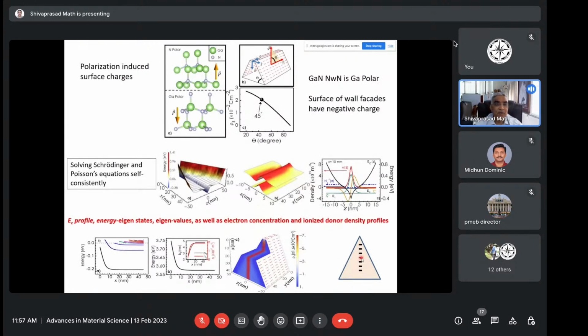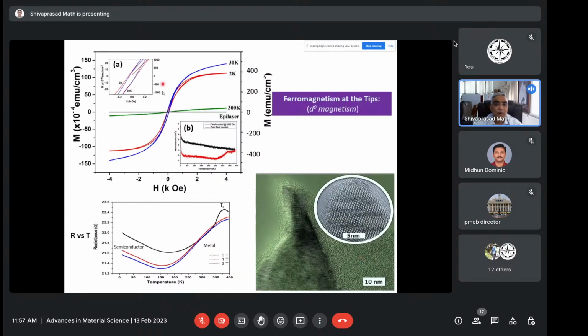Then obviously Professor Rao and Sundaresan had come out with many experiments to show some of the nanomaterials display ferromagnetism, even oxide materials, which are not expected to be magnetic, because of the surface dangling bonds. So we also wanted to see if these materials show ferromagnetism. Yes, we did see ferromagnetism. And then we did some careful study to understand how it shows. And that ferromagnetism, you see, it shows a TC above room temperature. That means I can get a ferromagnetic material out of these materials, which is above room temperature, which is amazing. A ferromagnetic material above room temperature, amazing, right? Amazing material you can see here.